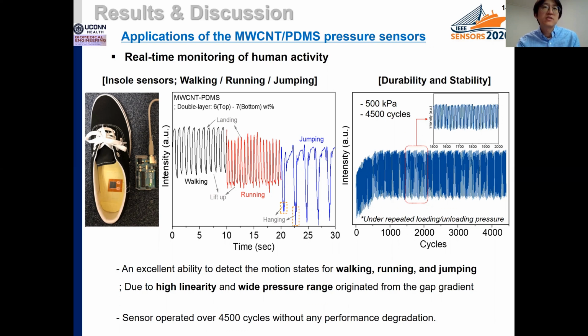Also, we did an operational stability test by applying 4500 cycles and 500 kilopascals of pressure to the sensors. As a result, the sensor operates stably without significant degradation. Accordingly, from the results, it's supposed that the stacked double layer pressure sensor could be applied in the field of wearable healthcare for human gait-related diseases.